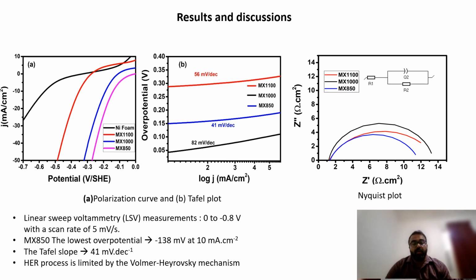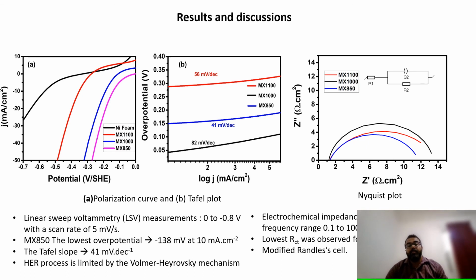To understand the mechanism of the system again, we have done electrochemical impedance spectroscopy and we have plotted a Nyquist plot. And from this we calculated the charge transfer resistance, which was in the order of 10.38 ohms, which is the lowest for a molybdenum carbide MXene based electrocatalyst. And this system was equivalent to a modified Randles cell.